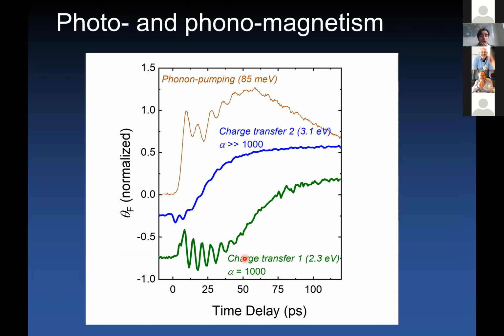When you excite a charge excitation in order to activate this Moriya transition, you're relying on heating of your electron system and then subsequent development of magnetization. So you see, this is this green curve shown here. This is spin dynamics induced by a charge transfer excitation, and you see that you can induce coherent precessions of your spins up to a certain point where you start to see a magnetization developing. Overall, it takes about 100 picoseconds for your magnetization to develop when you excite the electronic degrees of freedom.